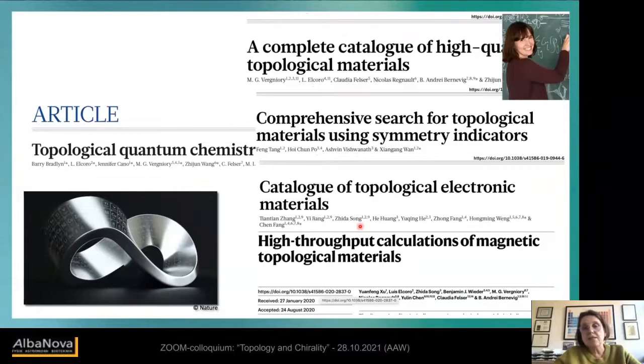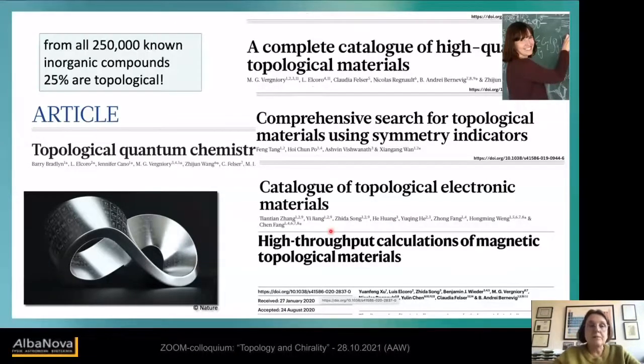From all the inorganic materials, they are all characterized now, whether they are topologically interesting or not, whether they're semi-metals, whether they are metals, enforced semi-metals, weak semi-metals, higher order topological materials, and even some magnetic materials were also recently investigated in this direction, whether they are topological or not. But the very surprising thing is that 25% of all the known inorganic compounds are topological, and this is quite a high number. If you thought at the beginning there were single